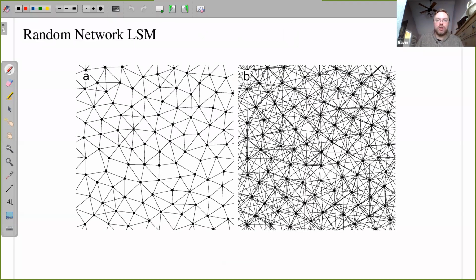So here's some of the structures I was doing. In order to map this on, you do want some semblance of symmetry. Let me just imagine a really idiotic scenario. Maybe you have something like this, and this node is only connected to bonds in one direction, going this way. Then there's nothing pulling it in the opposite direction. So there's no way you could ever map that onto linear elasticity theory. You do need an even spread of these to map it on.